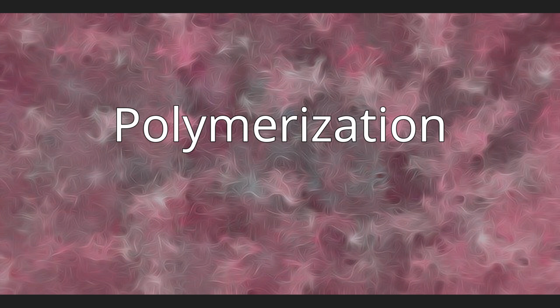This system suffers in practice. Electrophilic boranes activate the chelated nickel catalyst to oligomerize ethylene into a butylene. In the same pot, a titanium catalyst polymerizes ethylene and the olefin to form LLDPE. The degree of branching was found to increase linearly with the increase in concentration of the nickel catalyst.